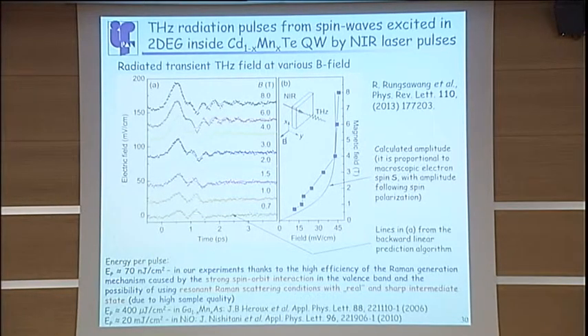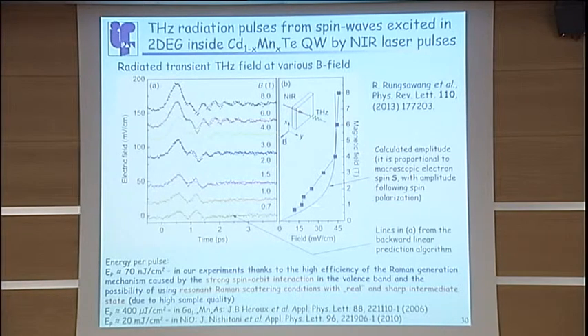For one sample, in the transient you can clearly see the terahertz radiation for different magnetic field values, and the amplitude increases with the magnetic field, which you expect because you are raising the polarization of the spin. So you can introduce macroscopic spin, and this is proportional to the macroscopic spin.